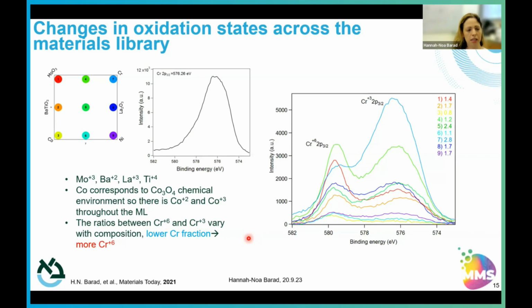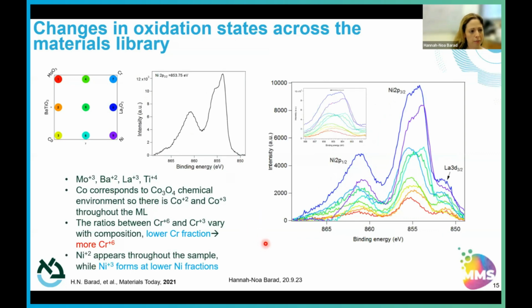So chromium +6 is the less stable oxidation state versus the chromium +3. And what we see over the evolution is that we get more of the unstable state as we go farther away from the chromium source, so the chromium edge of the materials library. And the same thing actually happens for nickel. So we get both nickel +2 and nickel +3 that changes with the gradient in position.